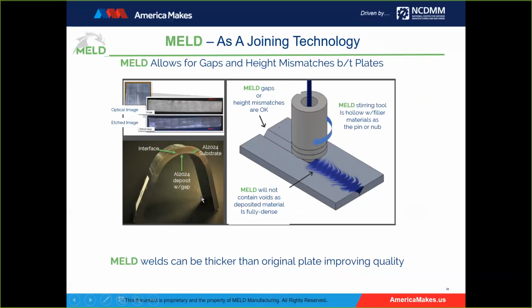No delamination or cracking after we completed the process. Via optical or an etched image, you see no signs of the joining. So again, what's important here is that we can serve the same capabilities as friction stir welding, but now with plate height mismatches or a gap for thicker welds.